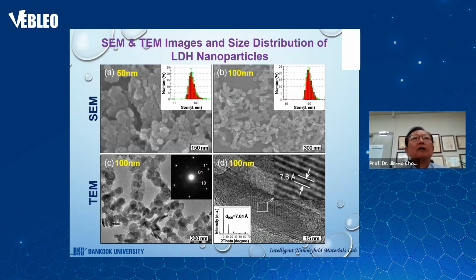Here you have the results of 50 nanometer sized LDH. This 50 nanometer sized pristine LDH was synthesized by the co-precipitation method, as I mentioned before. It is very simple. A solution of magnesium nitrate and aluminum nitrate was titrated with NaOH and sodium bicarbonate solution to maintain the pH around 9.5 with vigorous stirring for 24 hours. For 100 nanometer sized pristine LDH, the titrated solution was then followed by hydrothermal treatment at 100 degrees C for 16 hours.